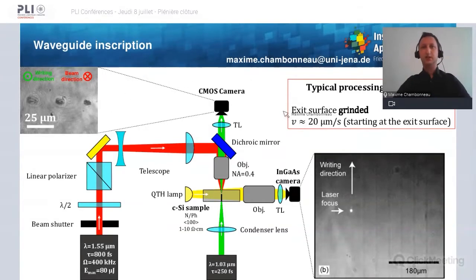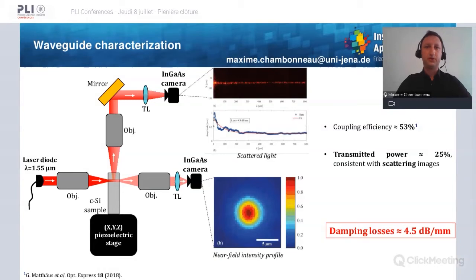Well, we work here with an exit surface which is grinded, like a very bad polishing. And then by focusing the beam at the exit surface, we can create some kind of crater, and then we move the focus upstream the laser towards the bulk of the material. And by doing so, we could inscribe some lines, and we checked the waveguiding properties with this simple setup here, relying on continuous light injection inside the waveguides with two different microscopes, one allowing to image the near field intensity profile, and the second one allowing us to monitor the scattering.